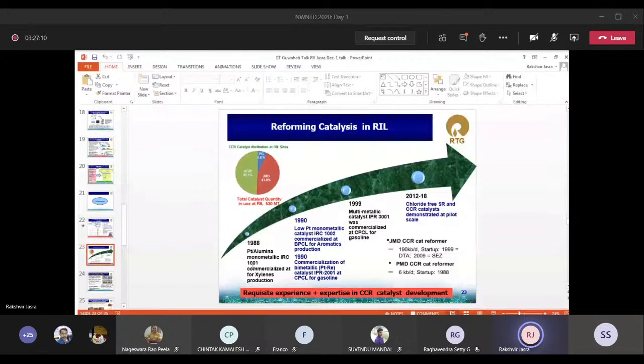Chloride-free means normally everybody in the world uses alumina, which is chlorided to provide acidity, and on which they put platinum and tin. Now we have put no chloride on this alumina, which is a big development, because when you put chloride, downstream units can get corroded, a lot of problems come. And a chloride-free CCR catalyst is a dream for everybody. So we developed it. Now how did we do it?